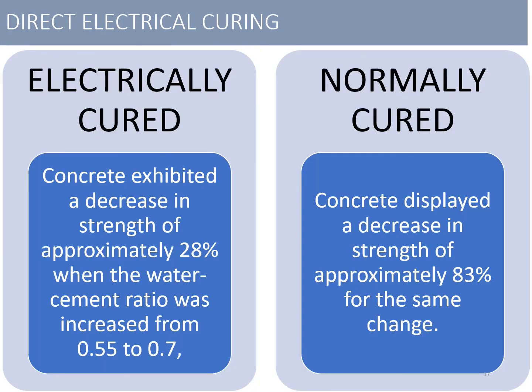When you compare electrically cured concrete and normally cured concrete, electrically cured concrete exhibits a decrease in strength of approximately 28% when the water cement ratio was increased from 0.55 to 0.7, whereas for normally cured concrete, with the same change of water cement ratio, the decrease in strength is almost 83%.